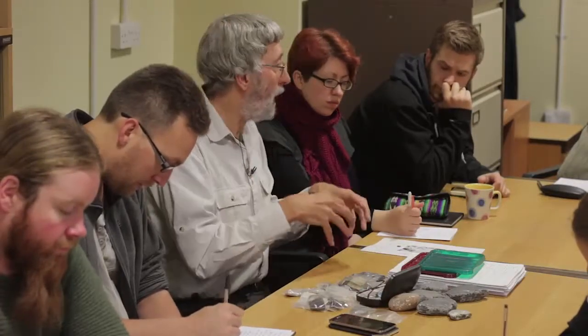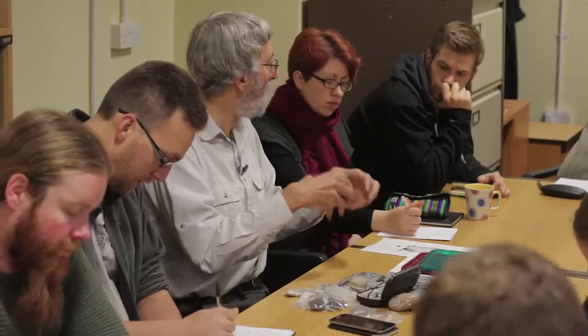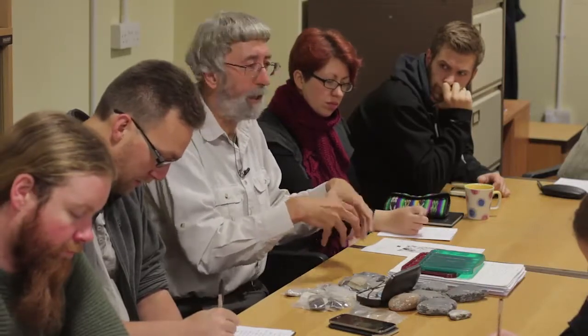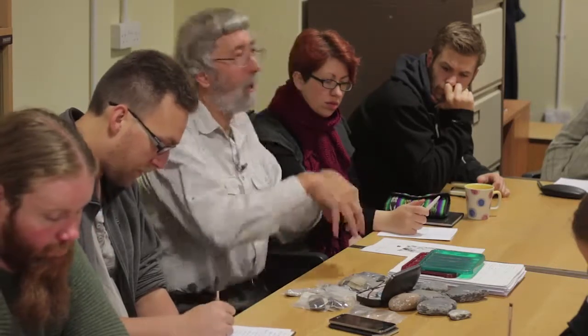The problem with heat treating is that you can go too far, and the flint will shatter and break. And you will find calcined, broken, shattered, frost fractured or heat fractured flints on a site. You'll find them crazed, like crazed porcelain, and they'll go white. Right? Because it's driving off the water, cracking the surface, and it's reflecting all the light back. So you get heat cracked flints on sites.